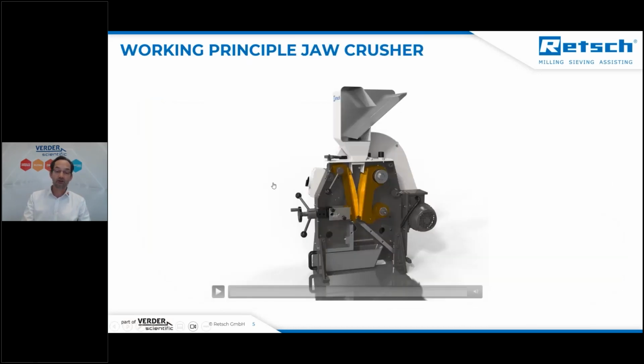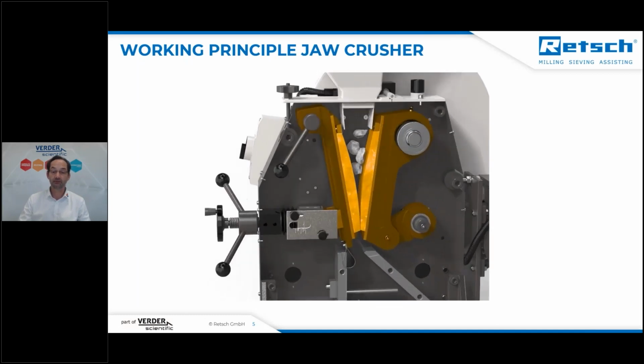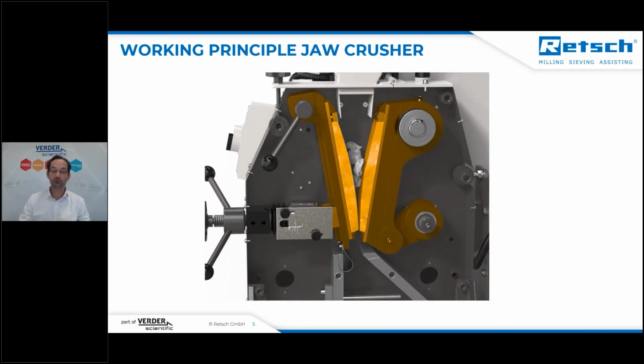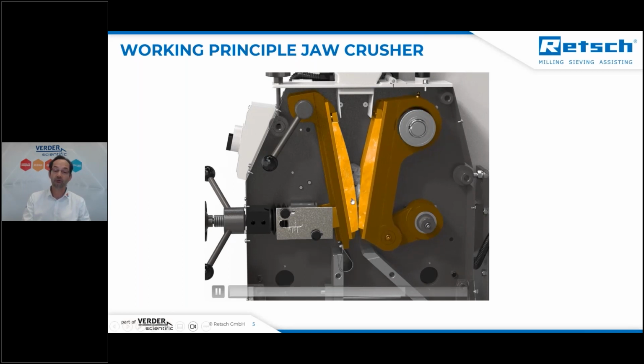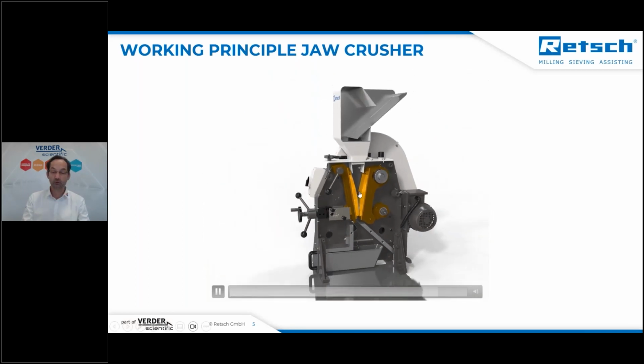As you can see here, this is another jaw crusher shown, but this just shows the grinding mechanism. The particles drop from the top into this hopper into the grinding chamber. And there's one jaw which is moving and is decreasing and opening a gap towards the other jaw. And then the material drops into this crushing chamber and is ground by pressure between the 2 jaws until this material is fine enough to pass the gap at the bottom and drop into the collecting receptacle.